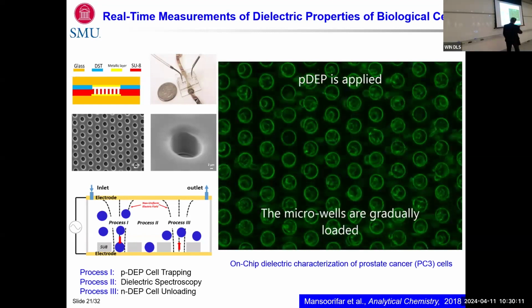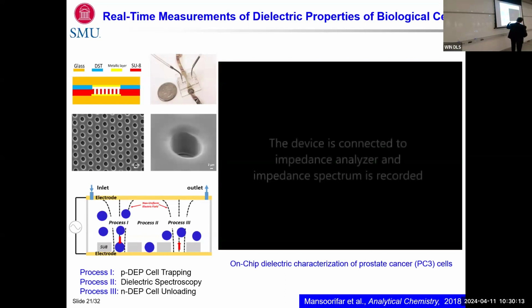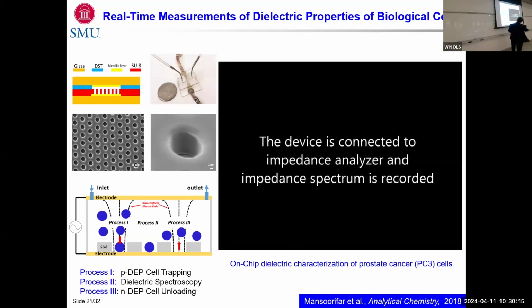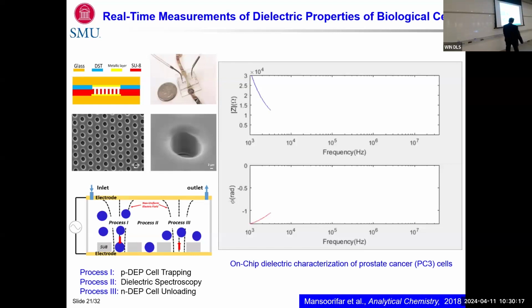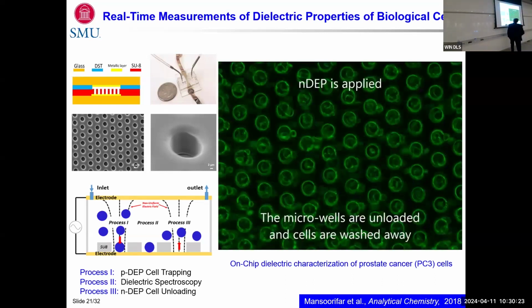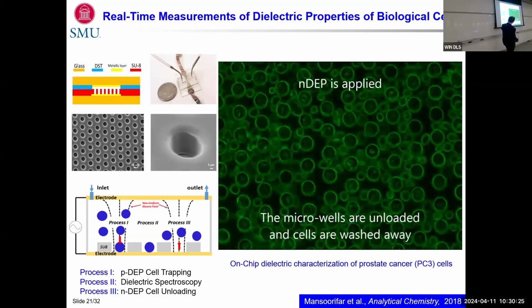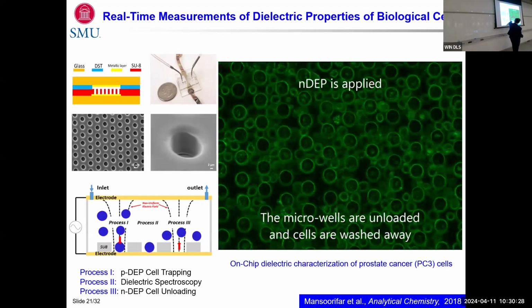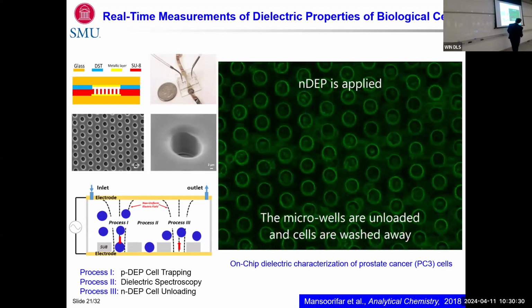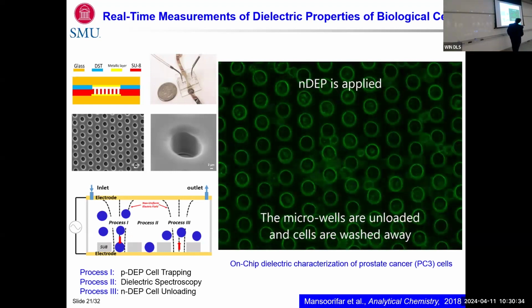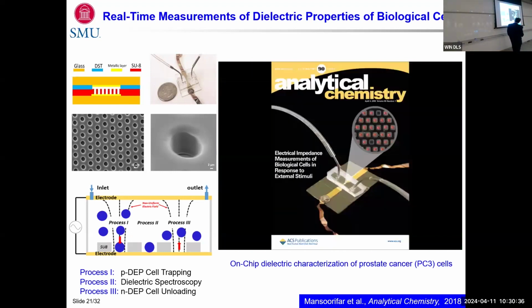The micro-wells are gradually loaded as the fluid is basically ballistically coming from right to left. And then we turn on our impedance measurement. Here's the magnitude versus the phase angle, and you have to study that. And then switching the electric field, you will see that these are being emptied. It is not a very clean movie because of things passing by, but it works to a degree.